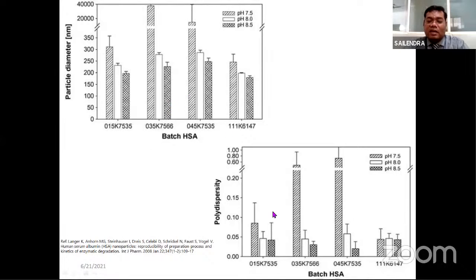And at the same time, if you see the polydispersity profile at different pH, this pH 7.5 is giving very high polydispersity, and these error bars are very huge. For 8.5, we have an error bar somewhat close to this one, but the polydispersity is comparatively low compared to pH 7.5. In this batch, the polydispersity for 8.5 is somewhere around 0.025, and here it is somewhere around 1. So there is a huge difference in particle size if you are preparing the nanoparticles at a particular pH, like 8.5 or 7.5.